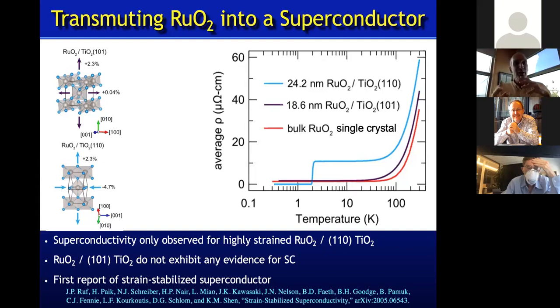Okay. So the way that we've done different strains is by using different faces of that rutile substrate. And on the 110 face, if it were fully commensurate, it would correspond to compressing the C-axis of ruthenium oxide by 4.7% and stretching it in the plane by about 2.3%. Here's another orientation to compare it to, and these both have fairly low surface energy, so they're good directions to grow in. The 101 direction is a much lower strain in comparison, so it's about 2% in one direction and close to 0 in the other direction. Okay, and you can see the big change that it makes.